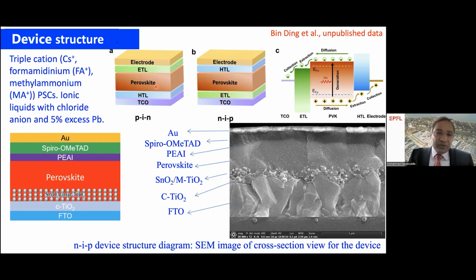In the other case, the PIN configuration, the light passes through the hole transport material, followed by the perovskite and the electron transport material. Therefore, one of the main conditions is that the hole transport material has to be extremely transparent so that you don't lose light absorption in the charge transport layers. In these two configurations, the highest efficiency of the NIP configuration is 25.7%, reported by Korean scientists. In the PIN configuration, very recently, scientists have reported 24.3% efficiency.